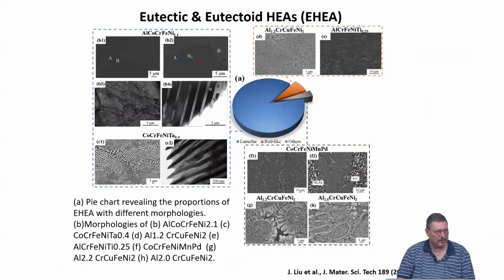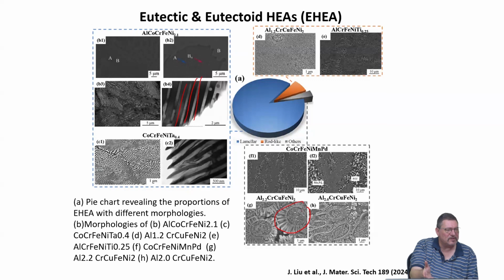what you also get in eutectic high entropy alloys. Depends again on how you design the system in terms of composition and how you design the process going from liquid to solid and doing or not doing post-processing treatment. And you can nicely see some of the eutectic features which you get are really very, very much as textbook-like, right? So you wouldn't see from the microstructure that these are high entropy alloys, right?